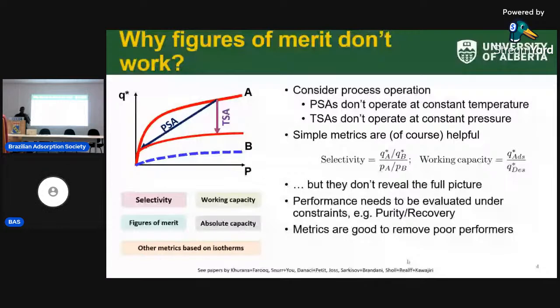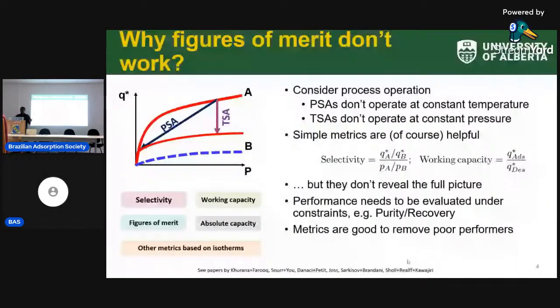But if you now ask, what is better when you put it in a process, you will immediately find out that it is always better to make nitrogen weakly adsorbed as compared to making CO2 strongly adsorbed. Because we usually have fixed surface areas, if you're increasing affinity, you're essentially making your isotherm sharp. From an operational perspective, I need to go to extremely low vacuum that is almost unattainable. So that kind of information does not typically show up in these very simple metrics because they don't tell you much about what happens when you have to build a process.